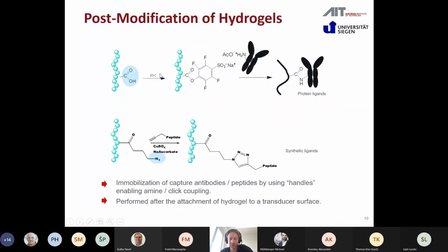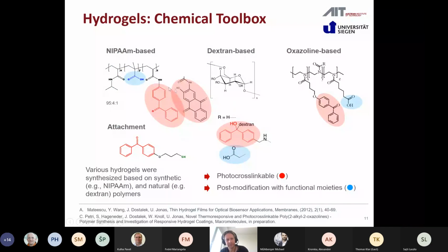These polymer chains, which serve as the binding matrix, can be covalently post-modified with biofunctional molecules by using amine coupling, or more recently we use click chemistry if we use smaller molecules like short peptides. And in our lab, since many years, through collaboration with synthetic chemists, we have available a toolkit of various polymers, which are typically terpolymers or copolymers, where into the pre-synthesized chains we have already incorporated moieties we can use for the post-modification, and we like to make the polymer networks by photocross-linking. So we have these additional benzophenone or anthraquinone groups. And we can use synthetically made polymers like NIPAAm or oxazoline, or more natural polymers like dextran.